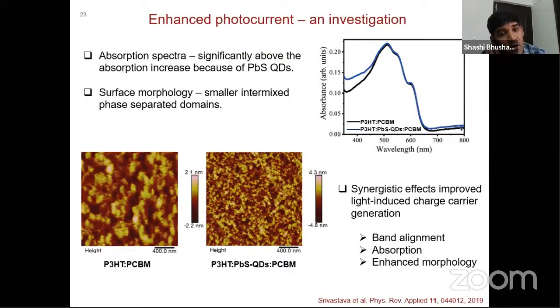Then for further understanding of why so much current increased because of the lead sulfide quantum dots, we saw that there is not much difference in the visible spectrum. Since the absorption doesn't have a significant increase, what could be the reason behind such a high current? So we went to AFM, checked the morphology, and found smaller intermixed phase-separated domains created because of the lead sulfide quantum dots. Because of these smaller domains, we found good transport of electrons. So you can say that band alignment was good, absorption not much, but there is enhanced morphology. Morphology was the critical point which gave us higher electrons at the interfaces.